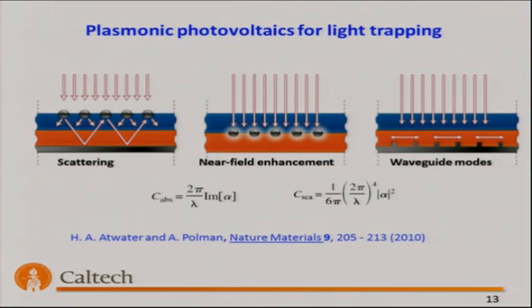Our group has also been spending quite a bit of time looking at small metal objects, in terms of their strong scattering and mode localization for localized surface plasmon modes, and also waveguide modes that take advantage of the fact that these metal objects have a very large and negative real part of the dielectric function, the permittivity, leading to strong scattering by metals.